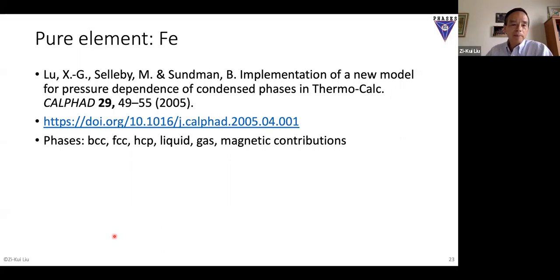So we take iron as an example. The iron system has been modeled many, many times. The last time it was modeled was 2005, by Bo Sundman, who is the developer of ThermoCalc and also the developer of OpenCalphad. And Martin Selleby and Xiaogang Lu, they revised the iron modeling to get a better volume model for 2005, that's the reference. So in iron, we typically have FCC, BCC, liquid, and gas phase.